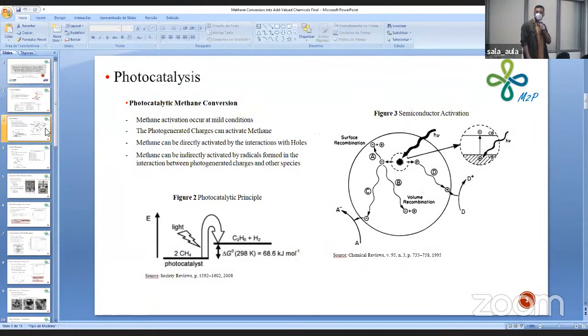We have then photocatalysis. The photocatalytic process is an alternative for methane conversion under mild conditions. Photocatalysis is based on semiconductor activation via UV light. And this way we can generate charges that can promote methyl radical formation. Here, in figure 3, we can see a scheme of the semiconductor activation.